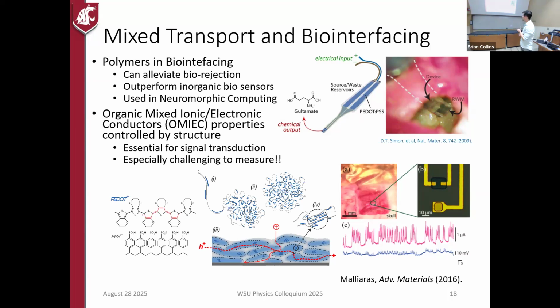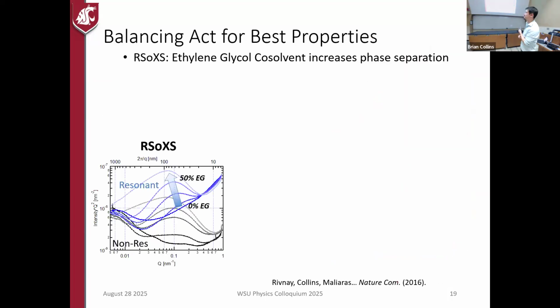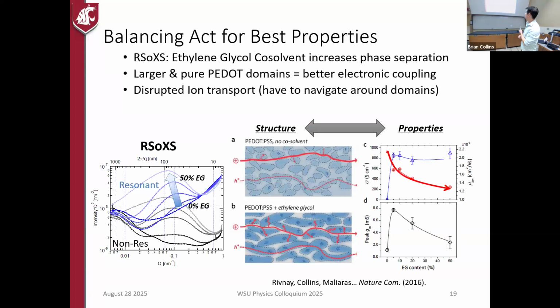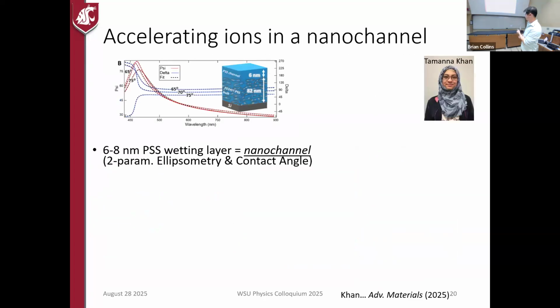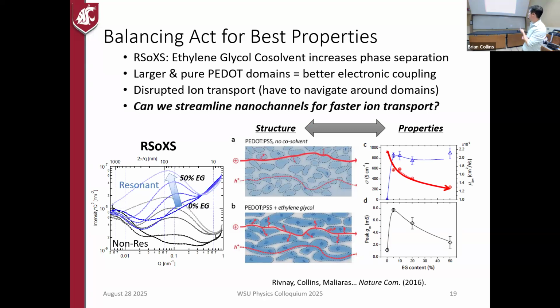And we think that's because you make these gel particles really dense, and the ions have to go around them, and it just takes too long to get around. So I'm going to skip some of this for time. The question really becomes, can we streamline these little channels for the ions to go through, make it easier for them to get through the device, so they don't slow down so much? Here's the ion mobility dying because these get too dense.